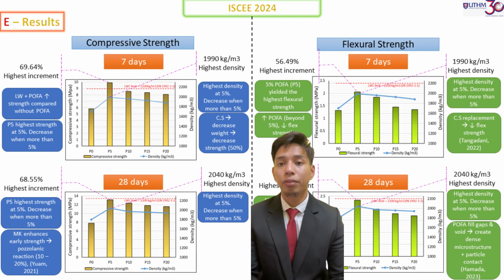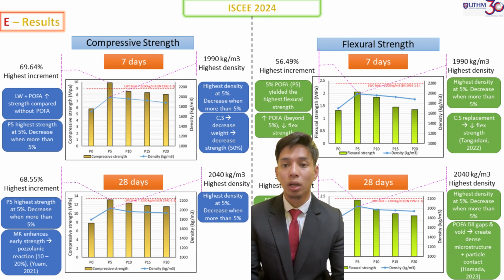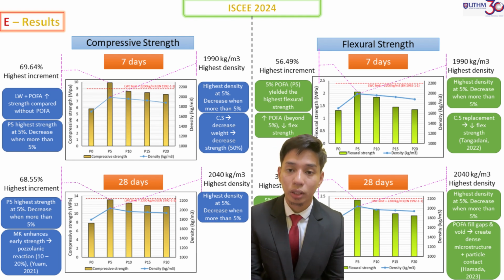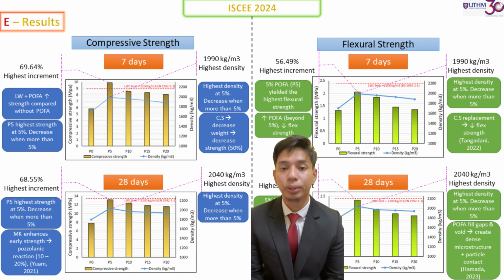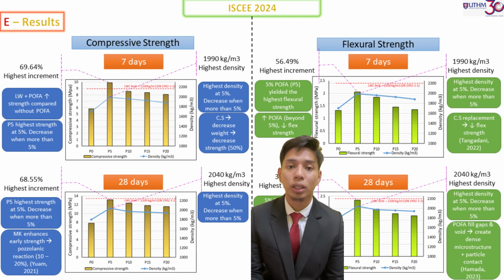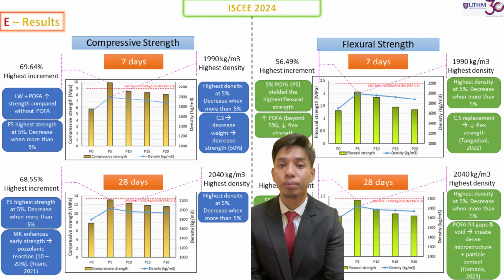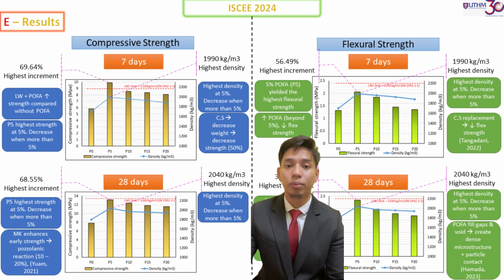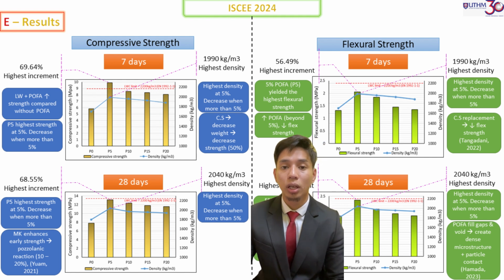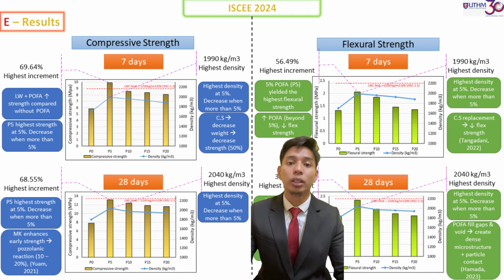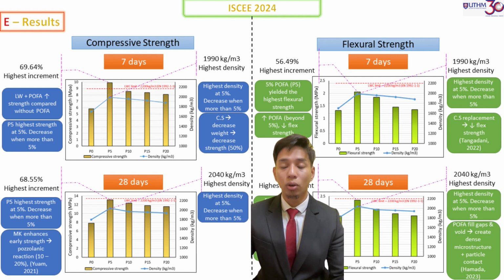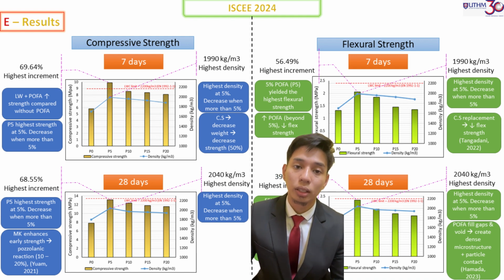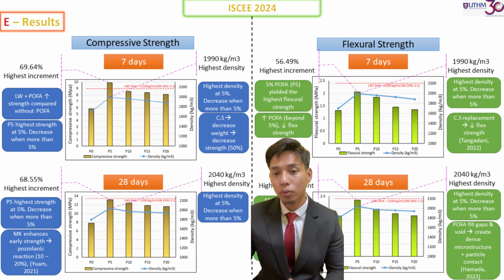So the P5 has the highest compressive strength at 5%, but the strength will decrease when the POFA content is increased. The density also belongs to the P5 with 1,990 kg per meter cube, which is the highest density, but the density will start to decrease when the POFA content is more than 5%. The pattern is shown in the graph, and the coconut shell will decrease the weight and also decrease the strength. Same goes for the 28 days.